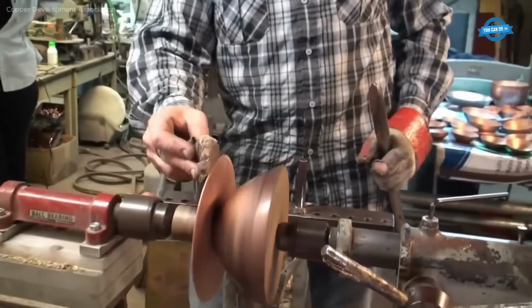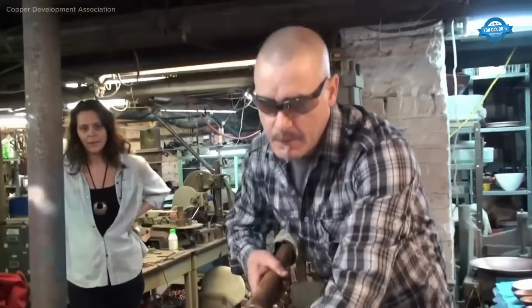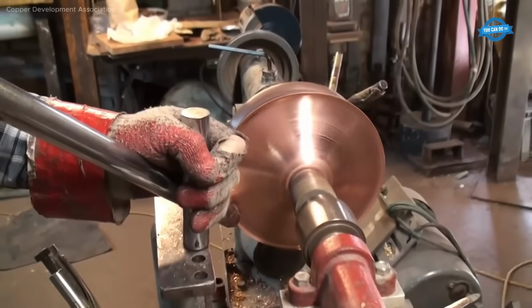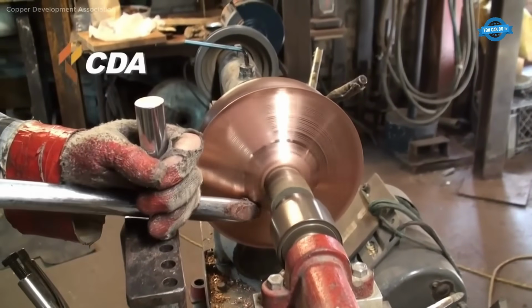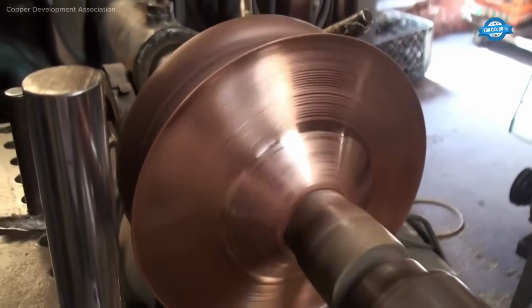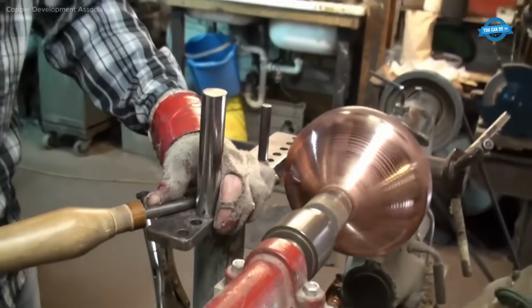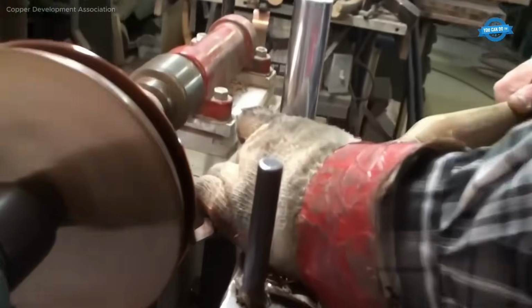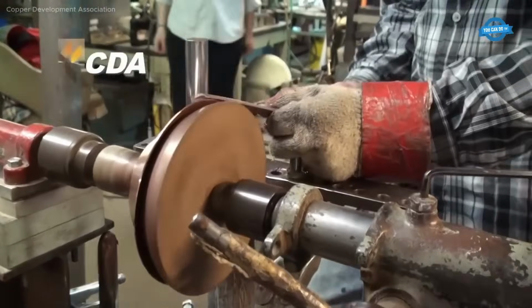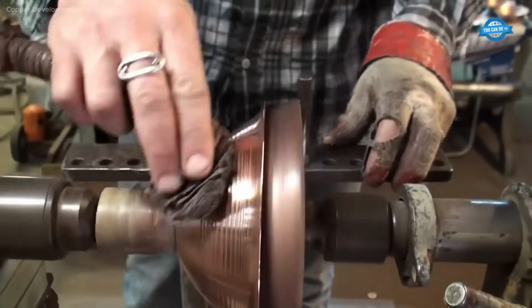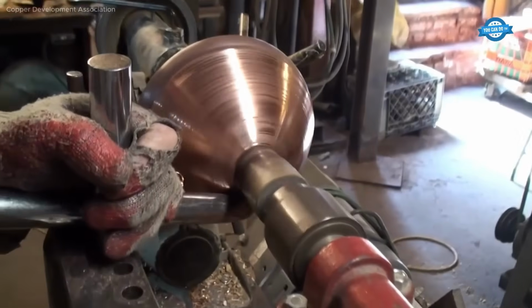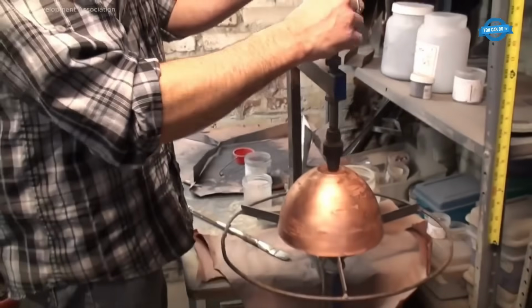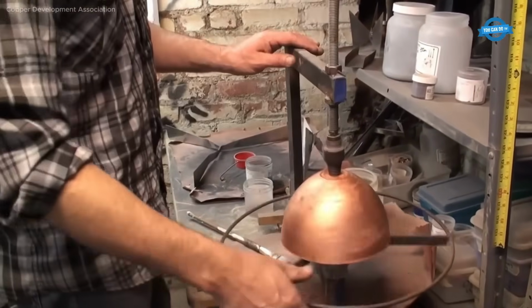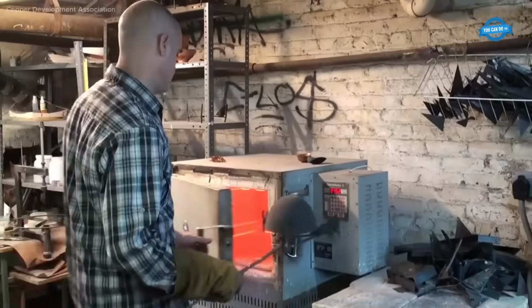To create an enamel copper bowl, a copper disc is clamped against a wooden form on a lathe. As the lathe spins, a steel tool shapes the copper over the mold. Wax is applied to reduce friction, and the rim is smoothed with a chisel and filed. The finished copper bowl is cleaned thoroughly to remove wax. A glucose-based clear fire mixture is applied, followed by a layer of fine enamel glass. The bowl is gently placed on a trivet and fired in a kiln, bonding the enamel to the copper for a smooth, colorful finish.